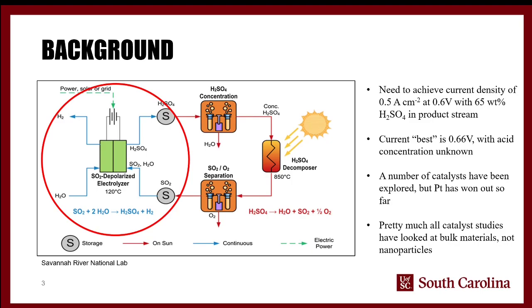So one interesting thing is that pretty much all the catalyst studies in the literature have looked at bulk materials, not nanoparticles. And for those who are not familiar with it, nanoparticulate catalysts tend to be much more active than their bulk versions. Gold is a fantastic example of this. Gold in its bulk form is more or less inert for the overwhelming majority of catalytic reactions. Once you make gold a nanoparticle, you get it down to a diameter of about 100 nanometers or less, it suddenly becomes very, very active for a number of reactions. And the smaller it goes, the more active it tends to be, up to a point.